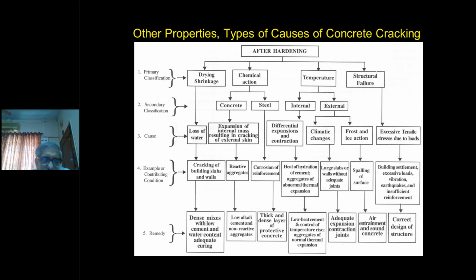But the other serious matter is the steel inside the concrete. Most often, proper cover is not given. Most often, the cover barriers which we use, the cover blocks, etc., they are porous, and instead of preventing water from entering and touching the steel inside the concrete, it allows the water to enter because it is porous. So corrosion of reinforcement starts taking place. In addition to water, sometimes sulfates and chlorides also enter the body of the concrete and attack the steel as well as concrete inside. And after some time, the protective layer is almost gone, cracks have widened, and this results in steel corrosion.